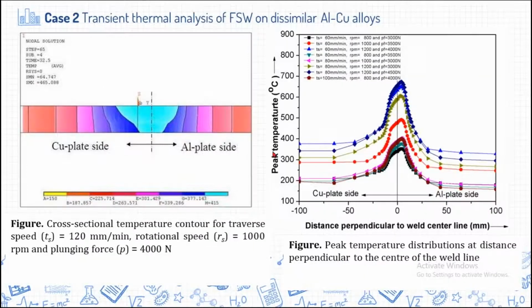And this is a simulation from side view, like a thickness point of view, copper side and aluminum side. This much portion, this is the center of the line. Actually, I need to keep this line out here. This is the center of the line, and this much portion is on the copper and the tool pin, and the entire area is on the aluminum side. So around 415 degrees centigrade we observed.